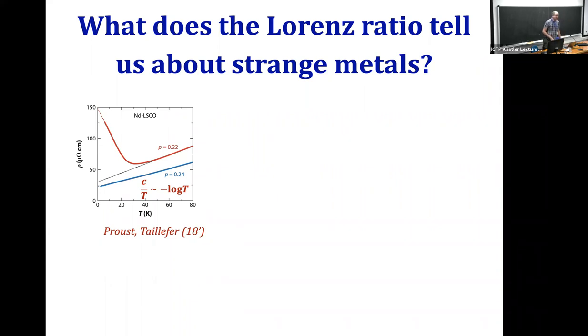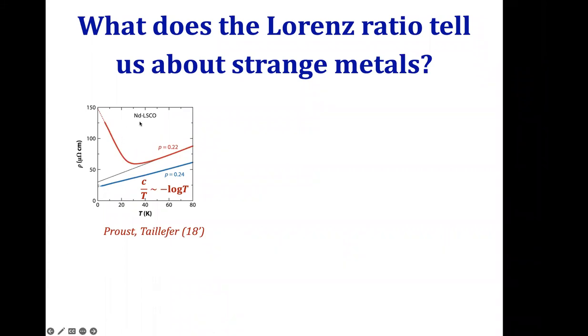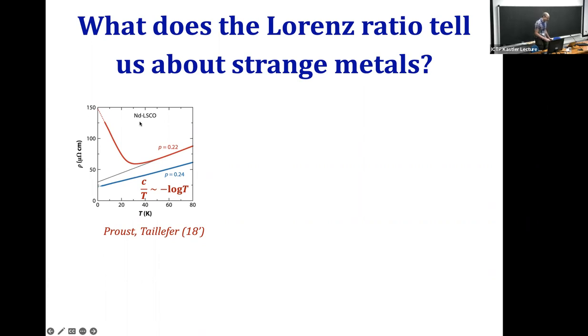Okay, so now we get to maybe the strangest of the strange metals. And here's a particular cuprate. This is a neodymium doped LSCO. And close to the so-called critical doping, the resistivity is actually linear on one hand down to extremely low temperature, and on the other hand, up to quite high temperature. This is clearly a violation of what we expect from a Fermi liquid. Moreover, at this value of the doping, the specific heat actually has a logarithmic singularity. It goes like T log T.